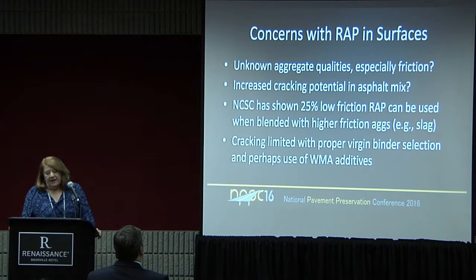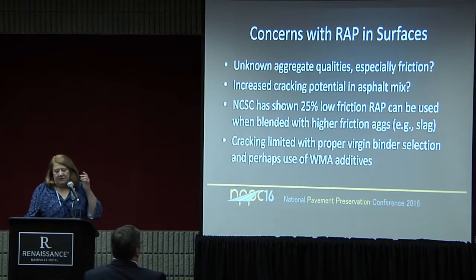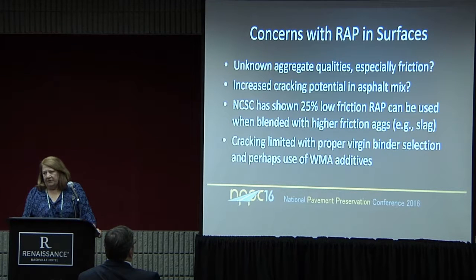We've done a lot of work on that at the North Central Superpave Center, looking at the frictional properties of wrap. We had to find a really crummy aggregate and make our own wrap because we wanted something that would polish very easily. And so we did a lot of work on that in the lab, looking at the friction with the worst possible aggregate you could find. And we found that if you blend it with a high quality material like slag for us, you can use quite a bit of this material.